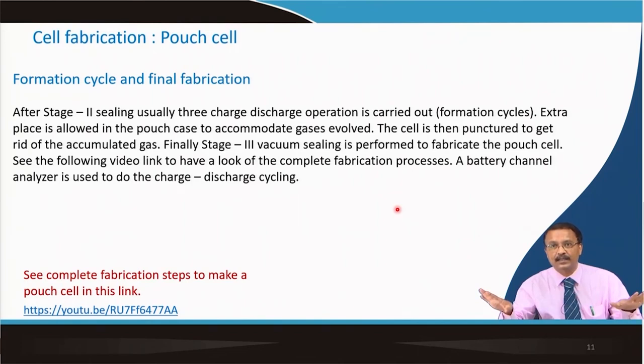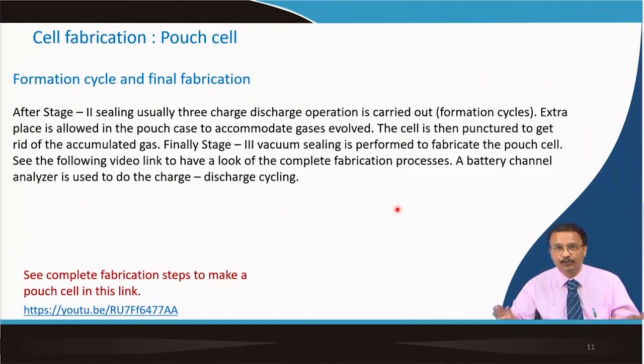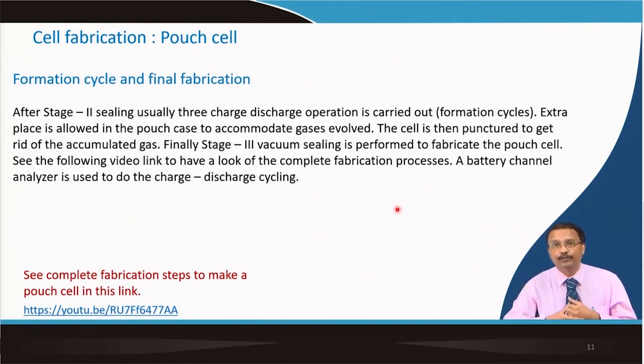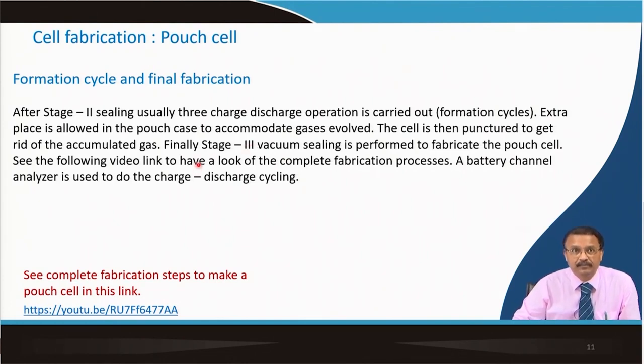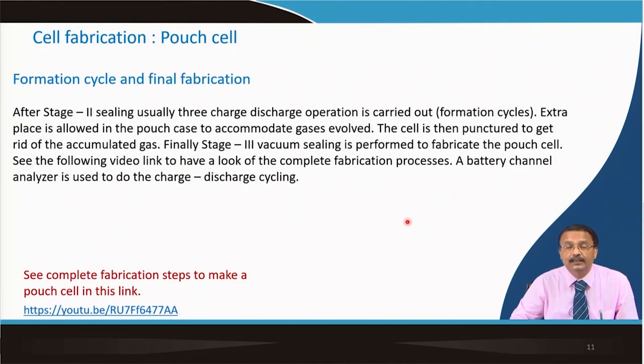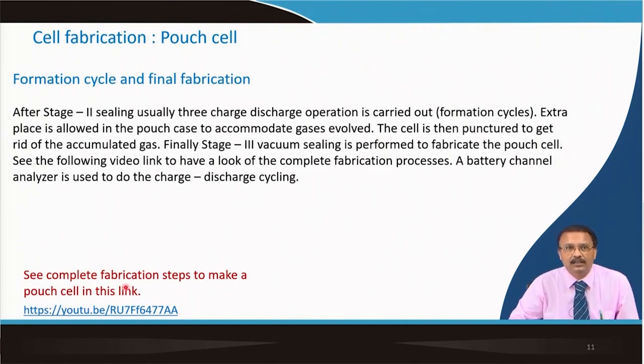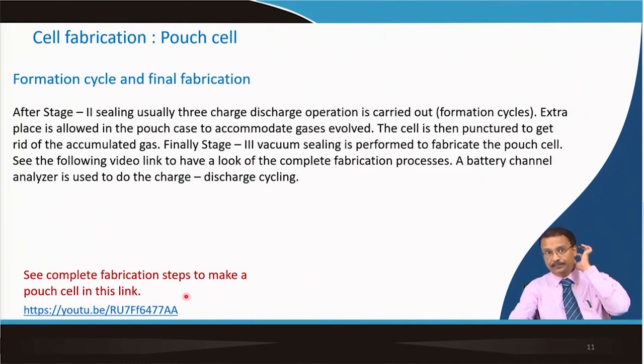You pierce the pouch so the gas comes out — there is no vent in the pouch cell. Then you do the third stage: the final vacuum sealing, so that there is no gas after the formation cycle. A stable SEI layer forms, and whatever gas was forming — we expect this is over within three to four cycles as long as the cell was swelling. Once you take it out the cell will not evolve more gaseous product. Then you seal it, cut the extra part with another machine, and you get the pouch cell. A battery channel analyzer is used to verify whether you are getting the expected 35 ampere-hour, 100 ampere-hour, or whatever capacity you predicted, and to confirm there is no swelling. Then it is fit for printing the company name, batch name, capacity, and voltage.